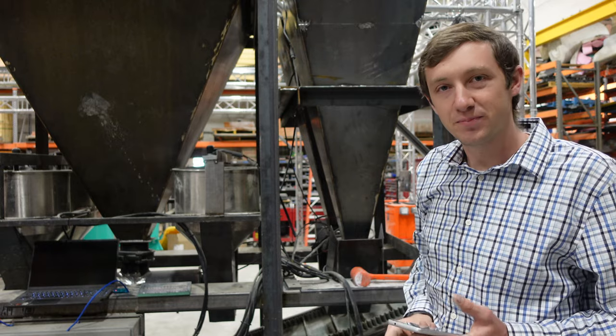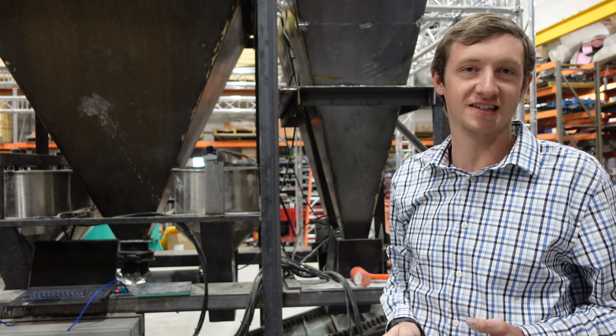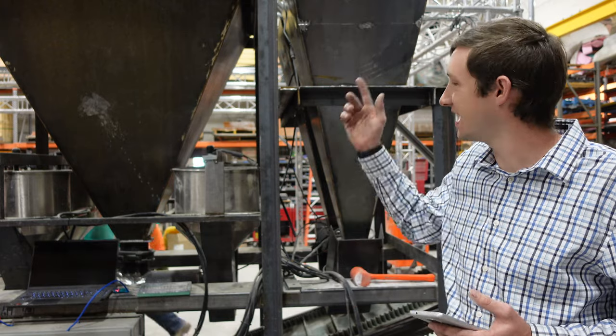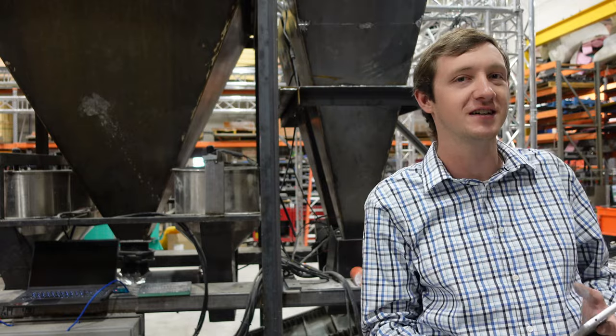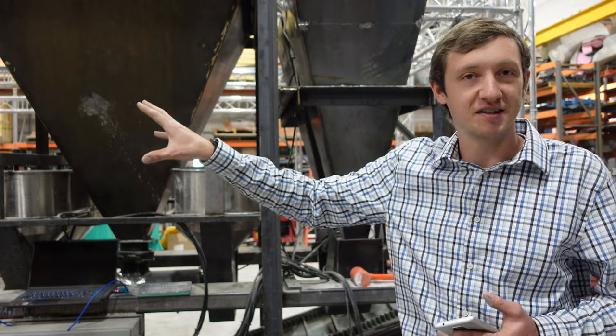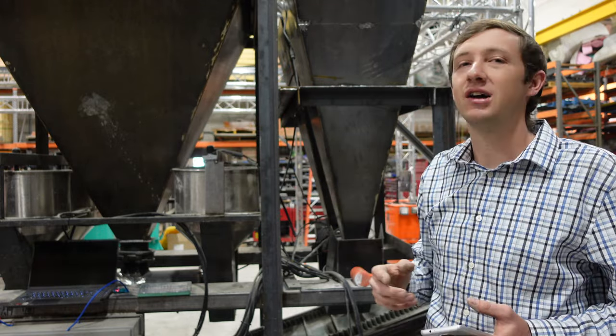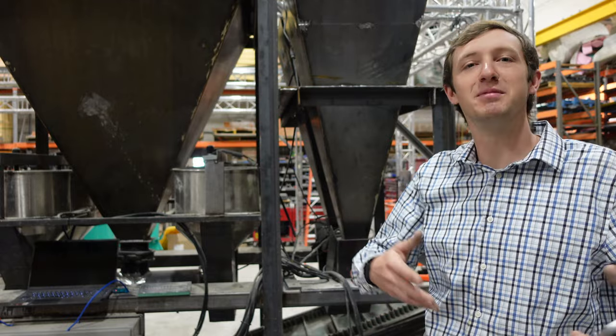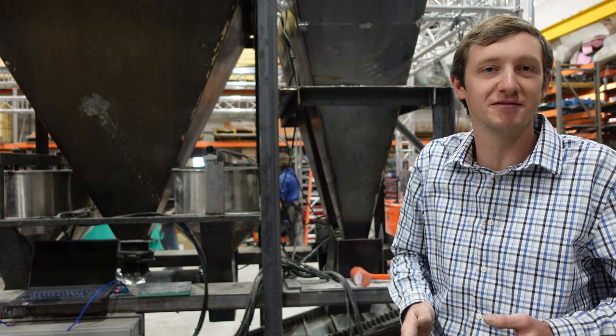One of the big challenges we had to overcome: wet sand does not like to go through a hopper, not at all. We came up with a couple of solutions — we've got an agitator in there, a nice wide opening at the bottom, and we went with an auger valve instead of a rotary butterfly valve. We also dry out our sand using a large ribbon mixer with a heater attached — it's basically a drying machine for your sand.